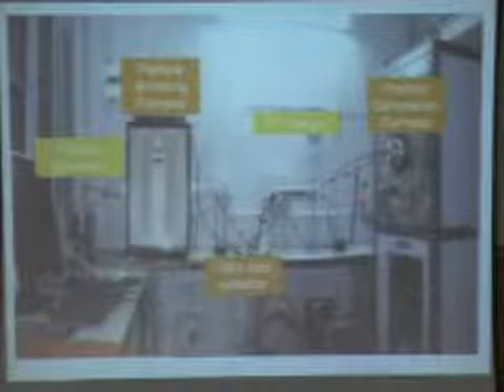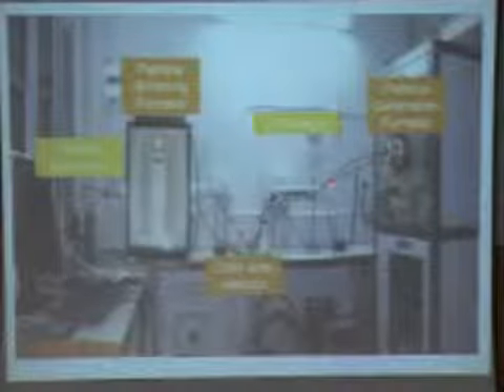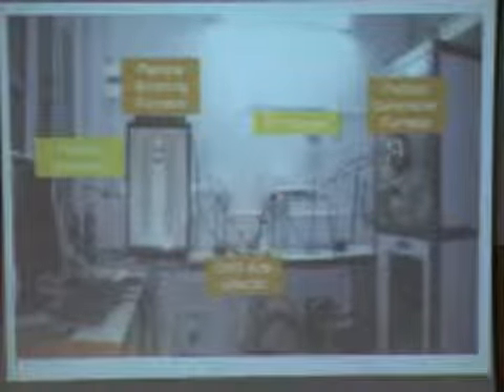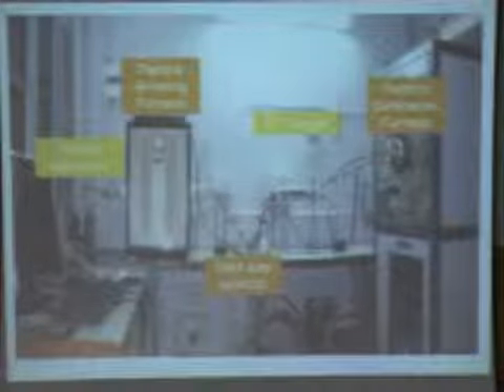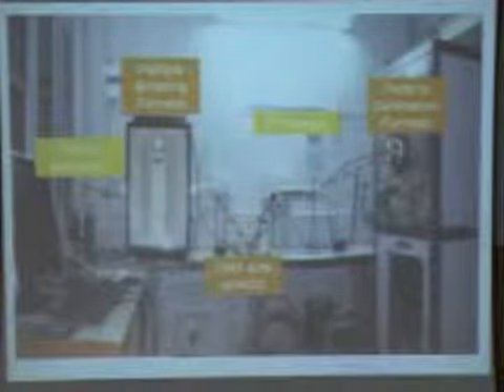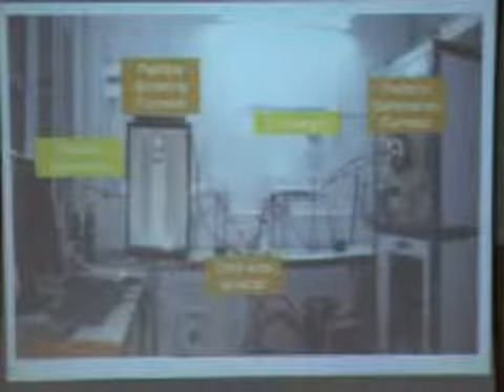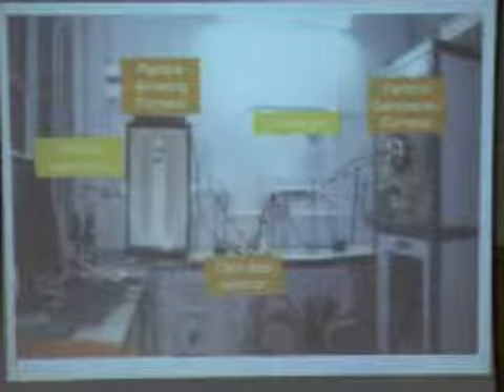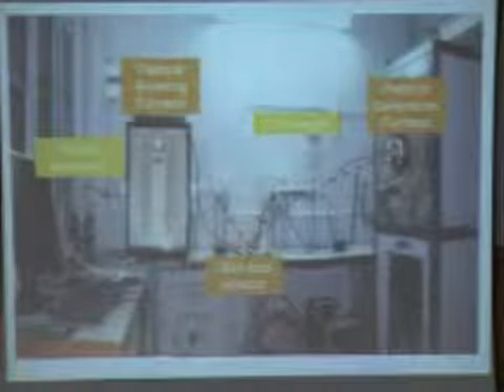Something like this. This is the experimental setup. You can see that this is the spark generator. The particles come through this pipe. This is the charger here. The tube takes the particles down. This is the differential mobility analyzer. It selects the size. Then they go through the sintering furnace. They enter here and they come out here, and here they get deposited in the chamber. And this is some sort of a computer which controls the deposition process.